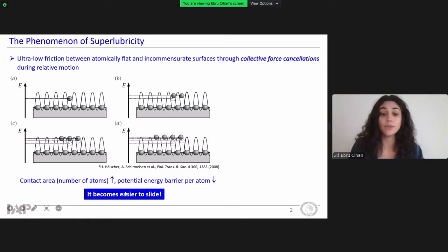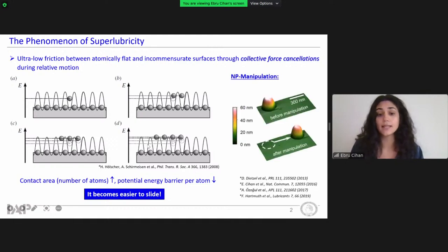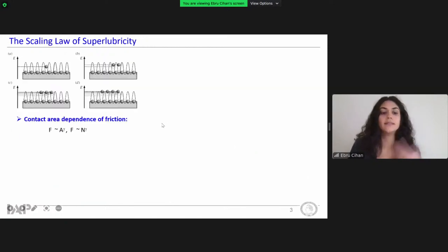At this point, it is very important to systematically analyze this phenomenon of superlubricity, and for this analysis, we need absolutely well-defined contact areas. So an alternative tool for this purpose would be to use nanoparticles with well-defined contact areas, which we can manipulate using an atomic force microscope tip on a flat substrate. Because then this will allow us to analyze sliding friction as a function of contact area, or number of atoms at the sliding interface, with a scaling factor of gamma.